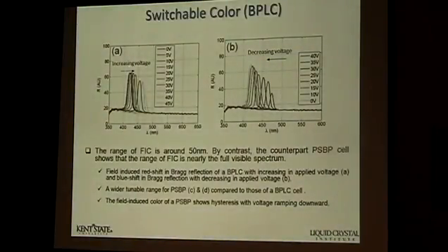For blue phase materials, without any other heterogeneous species put in, you can see that once you increase the voltage from 0 volt to about 45 volts, the cell gap is about 10 micron for this case. You apply the fields and you see that the Bragg reflection wavelengths do shift. This has been known for years. This is not the first discovery. They shift normally around 30 nanometers either way, depending on what kind of cell structure. With in-plane fields, you make the blue shift. If you have top-down electrodes, these top-down electric fields shift it to longer wavelengths by enlarging the lattice. In that case, you see the drop in this Bragg reflectivity too.